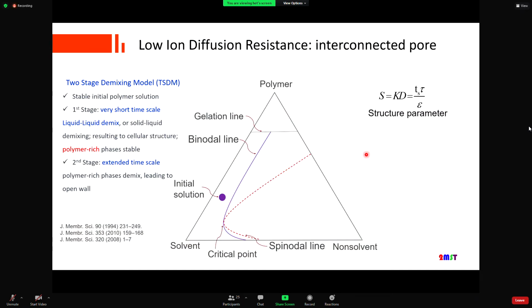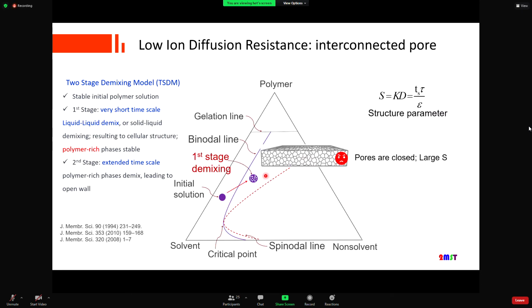To develop an interconnected pore, there is a model called the two-stage demixing model. I will give you a brief description of how this works. We started as the initial polymer solution. So when we have a liquid-liquid demixing or liquid-solid demixing, you will form a polymer lean phase and a polymer rich phase. At this stage, when you remove all the solvent, you will get a closed pore or cellular pore structure, which has a large structure parameter.